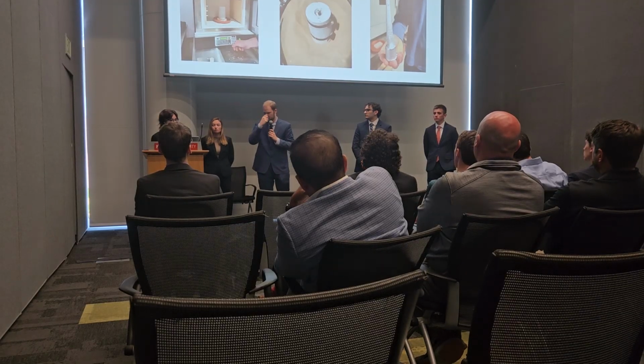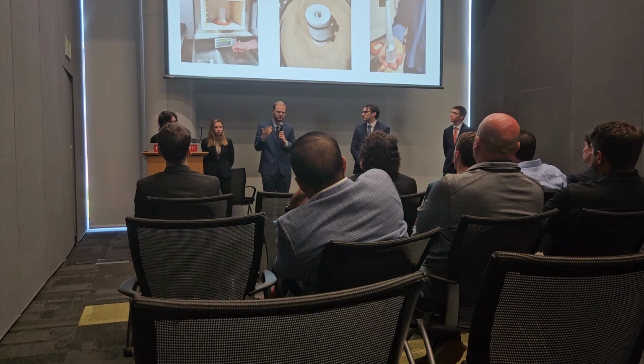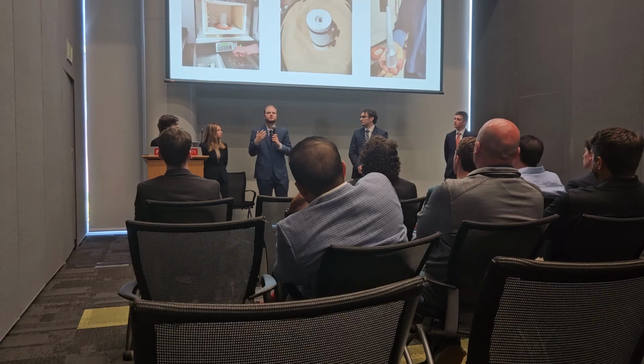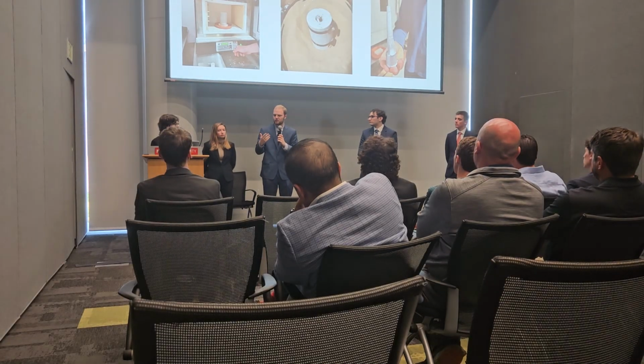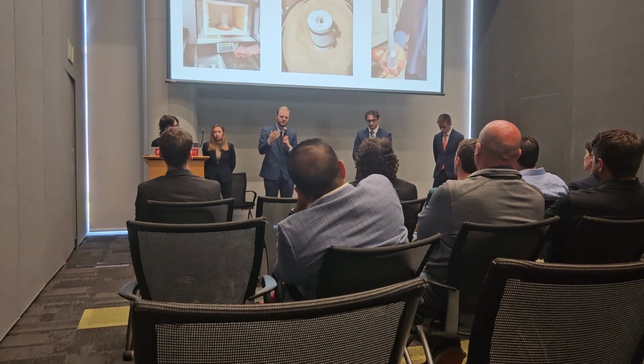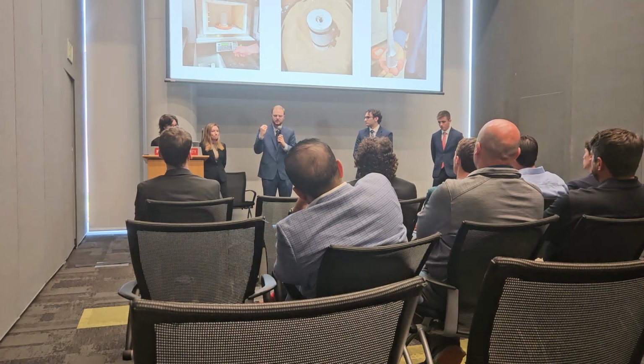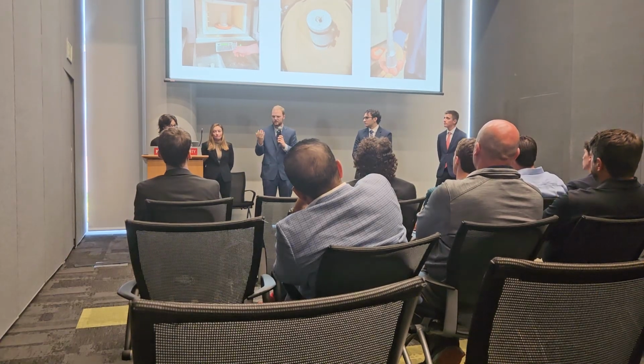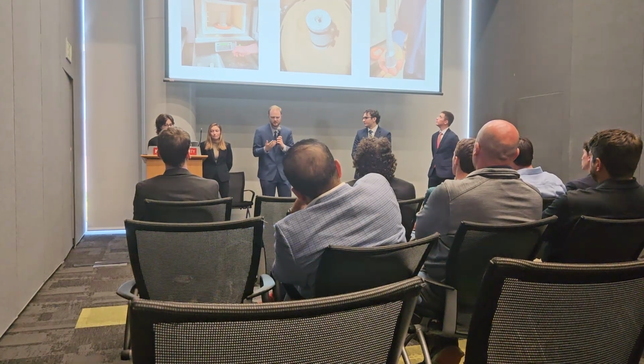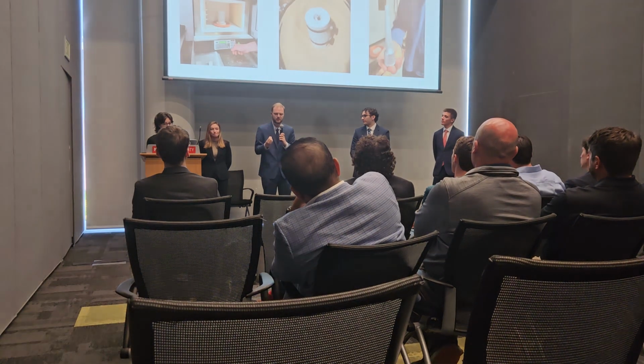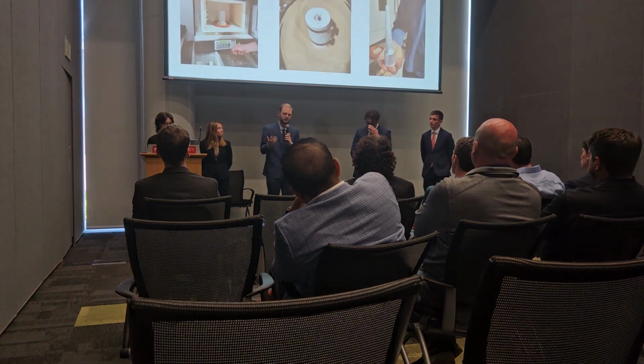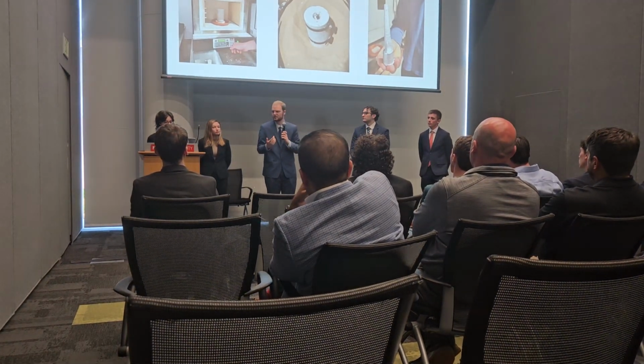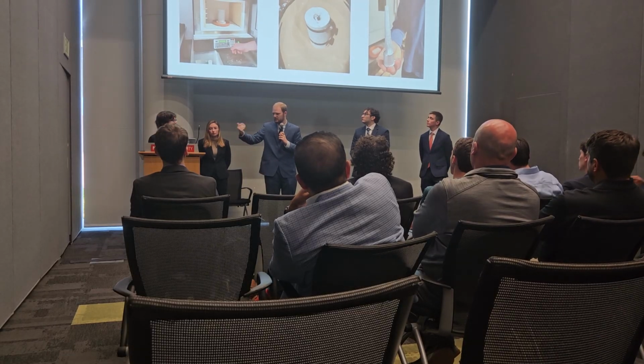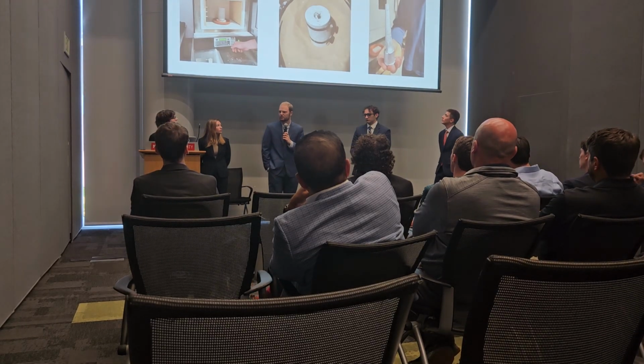Then after that, we have the metal pour. Once the wax is gone and there's a recess, we would pour the aluminum mixed with the aluminum nanocomposites directly into the preheated mold at 450C. We melted the aluminum at approximately 800 and poured it at 900C to maximize flowability. And as you can see at the end is the final cast part.